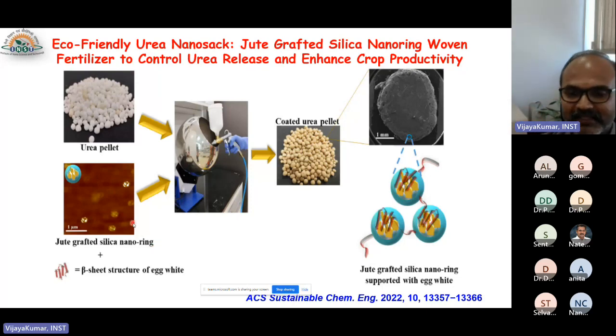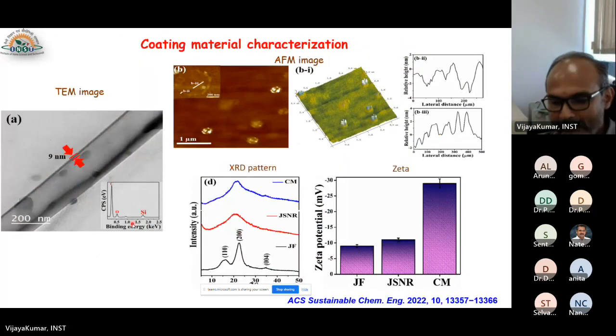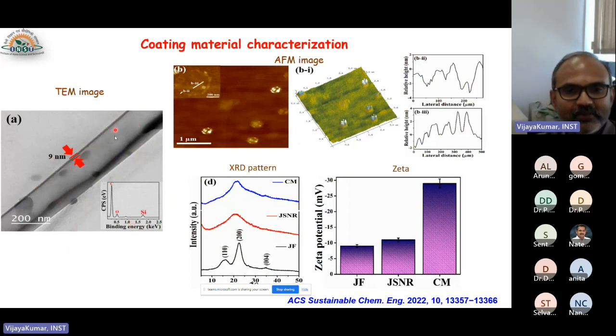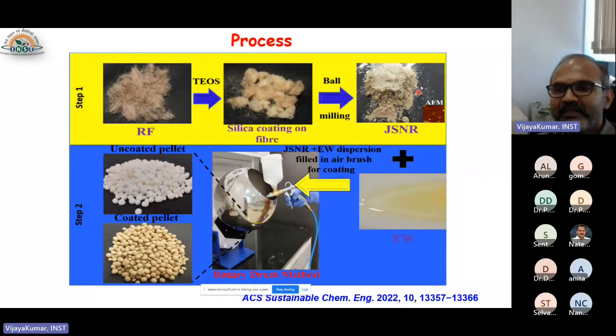Once it is milled, this is the jute fiber that has the silica coating. After coating, this is all different characterization. After milling, you get this kind of talc-like powder. It's a very fine powder. This fine powder has been mixed with the egg white.